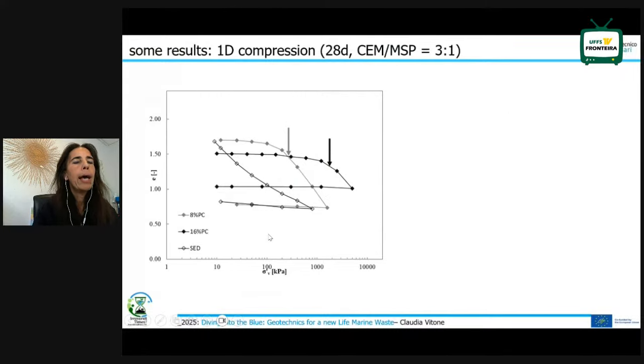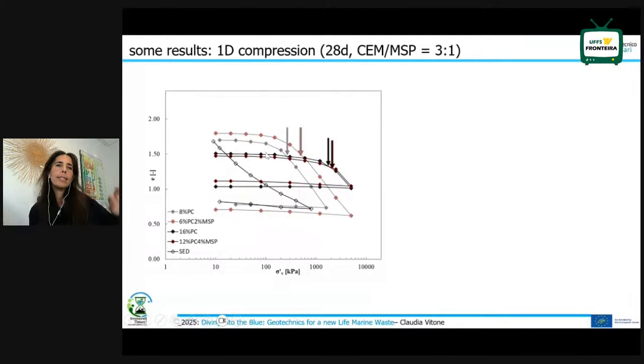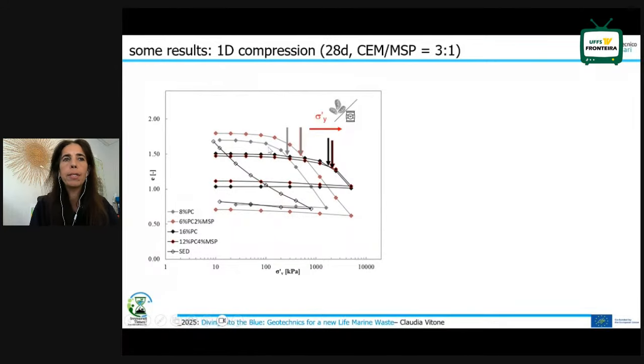Here we have again the oedometer test, in the void ratio versus vertical effective stress plot. This is the natural sediment. This is the control mixtures with the ordinary Portland cement, 8%. The black is 16%, the gray is 8%, and you can see now the red contour means the new solutions that essentially are quite similar. Essentially, it's a very good result.